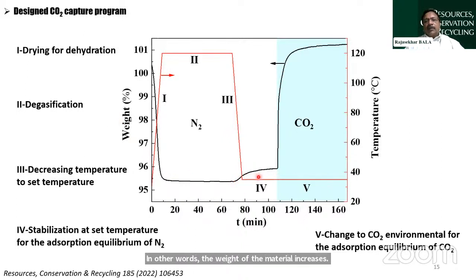The reason why the weight of the material increases is because it's able to remove nitrogen and keep it onto the surface. However, when the same material is introduced to carbon dioxide, the weight gain is much more significant as compared to nitrogen, which would indicate that our carbon foam is much more selective towards carbon dioxide as compared to nitrogen. Just imagine in the flue gas that we get from industries, you have a combination of both nitrogen and carbon dioxide. So if your material is going to be exposed to nitrogen more than carbon dioxide, then whatever active sites we have on the surface will be all saturated. And therefore, you may not be able to remove carbon dioxide anymore.